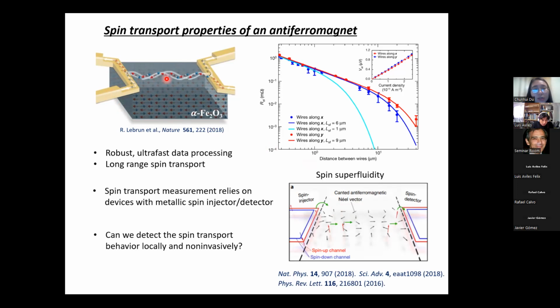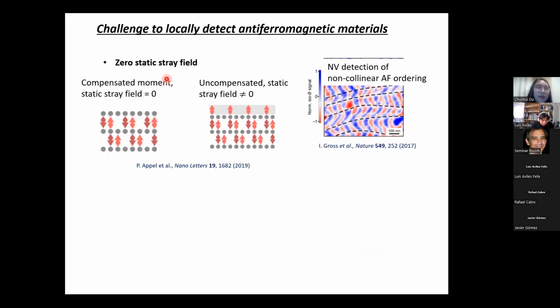Typically it's very hard to study antiferromagnetic material systems because if you have a compensated antiferromagnet, due to the antiparallel spin configuration, it generates a zero stray field. So we cannot use magnetometry to measure the antiferromagnet easily. To image it, it will require some uncompensated surface spins, which are typically also very small, or it requires that the material hosts non-collinear antiferromagnetic textures, like at the domain wall, or hosts non-collinear antiferromagnetic domains. So I will talk about the imaging of this type of antiferromagnetic material later in my talk.